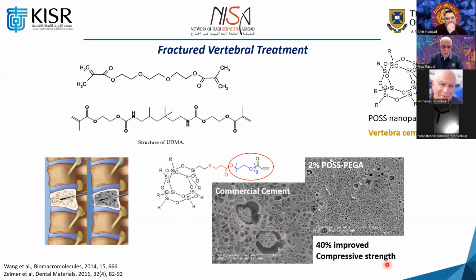Not only is compressive strength important in the vertebra repair, but also what is important during the polymerization. This material has low leachability and is non-toxic. Commercial cements will probably polymerize with a very high increase in the exotherm temperature, comparable to methyl methacrylate. So all these are advantages of using this type of monomers in combination in order to repair vertebra like that. So this is another biomedical application.